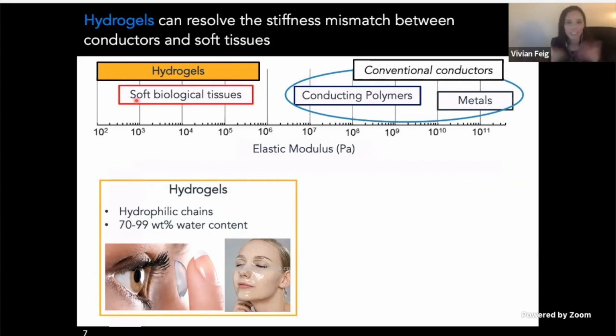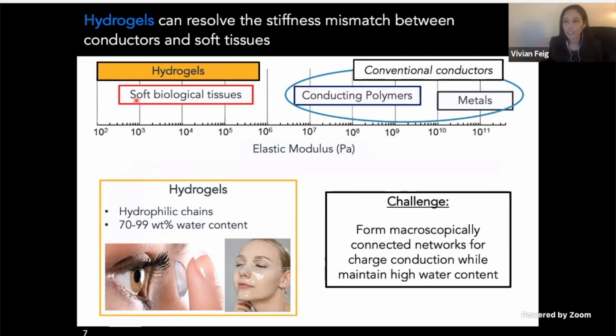products like facial masks. And so to make a hydrogel electrically conductive, the main design principle we came up with is that you have to form these macroscopically connected networks that can transmit electrical charge throughout the bulk of the material, while still maintaining that high water content that we want to achieve these tissue level modulus values.